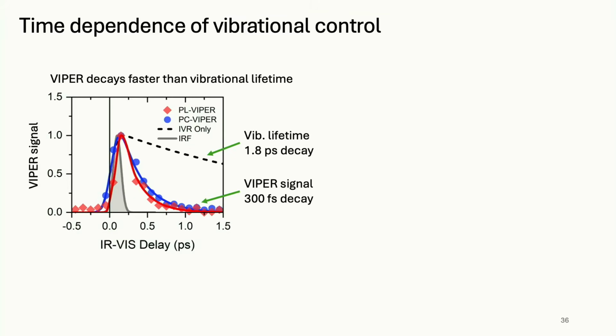Okay, so what I want to show you, basically, we asked why are these vibrations helping to excite electrons over the band gap? And so the vibrational lifetime is actually 1.8 picoseconds, which is very slow. The signal that they see decays in 300 femtoseconds. So we said, if you excite the vibration and it's still going for 1.8 picoseconds, why don't you keep having excitations? It turns out the crucial thing, remember, the molecule has the vibration, but the excited electron is on the backbone, the lead halide backbone. So how do those two things talk to each other? Through the gentlest of bonds, a hydrogen bond.